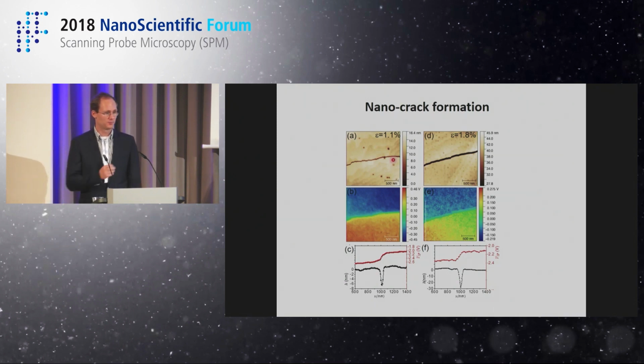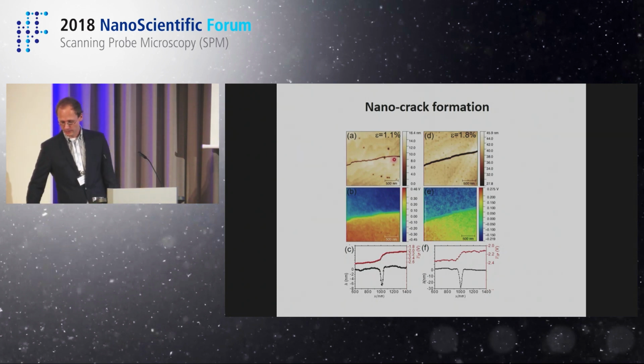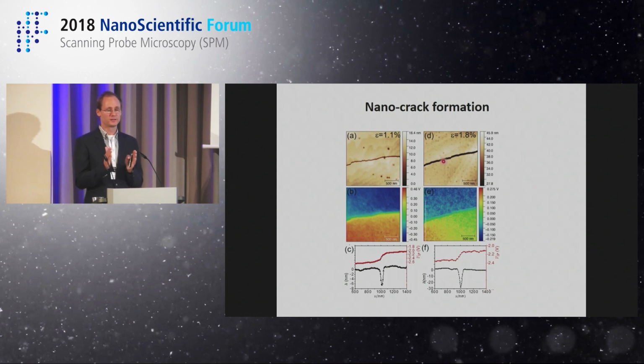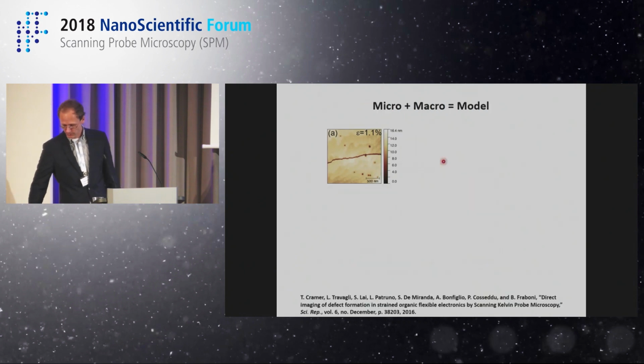Of course, there must be some physical origin of this defect. So what is happening is that this crystal cracks and creates this barrier, and indeed I can see that that's exactly where I have the buildup of the strong electric field. If I apply more strain, I can also see that these cracks widen. The rest of the crystal remains connected. It's just the crack that widens and absorbs the stress.